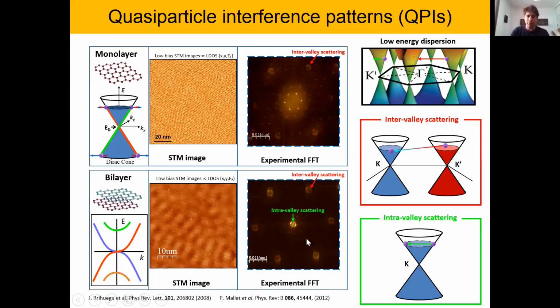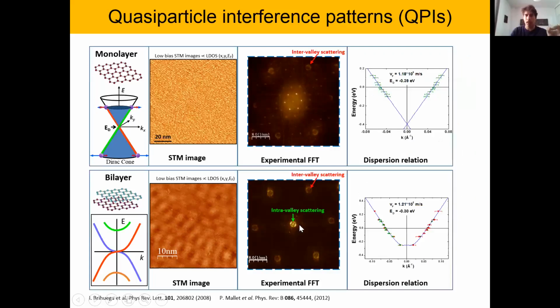And if we analyze this QPI now as a function of energy, these rings change size, and by analyzing the diameter of these rings, you can recover the band dispersion of both monolayer and bilayer and the most important parameters. Okay, so that's for the band dispersion, but it's not only how the bands disperse, whether they are linear or massive. We also have this additional degree of freedom, which is called the pseudospin. It is how this pseudospin rotates and the conservation of this pseudospin that are responsible for many of the important properties of graphene. And for example, you can see here how this reflects in the QPI.